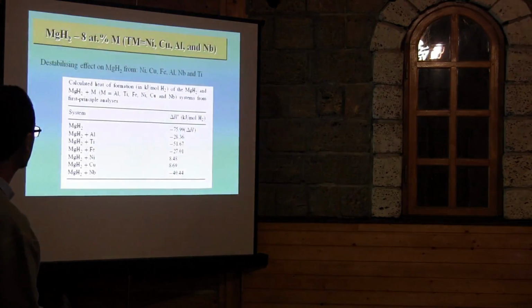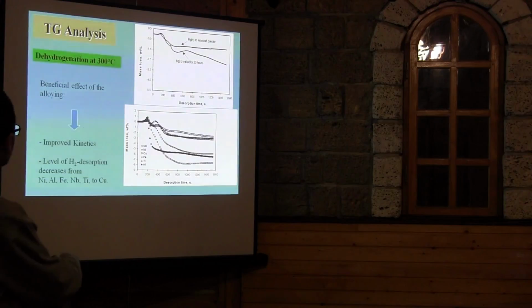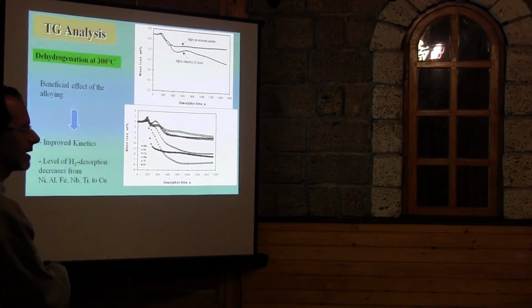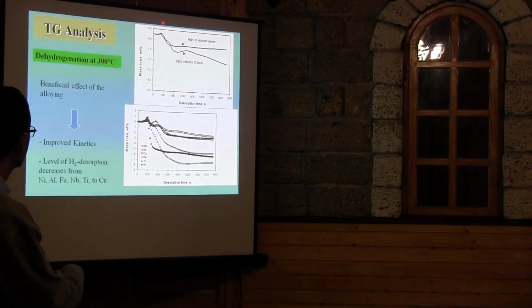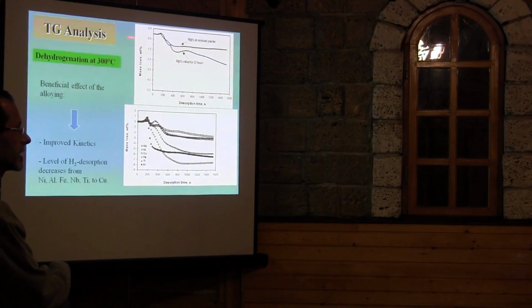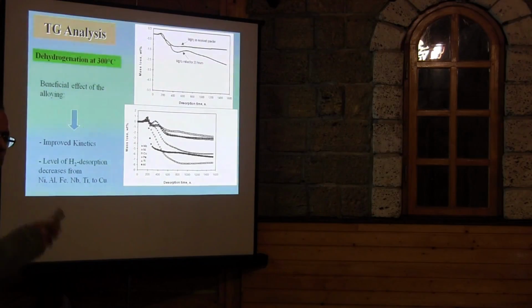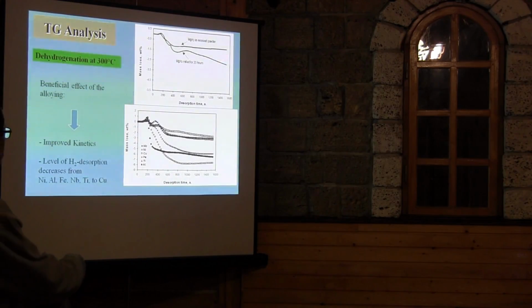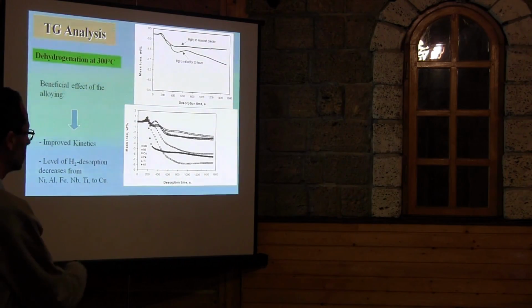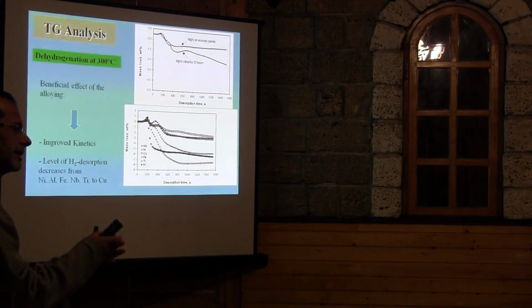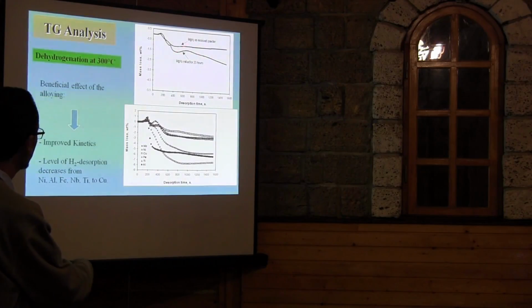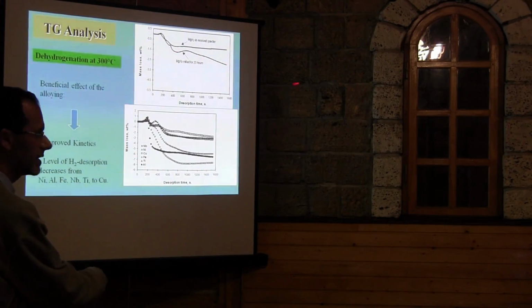Now, what is the thermodynamics of the system? I did what we call thermogravimetric analysis. I made the dehydrogenation at 300 Celsius. You can see, as received, when I buy magnesium hydride, it doesn't release hydrogen, even at 300. That's why I said it's very stable, and the kinetics is very slow. You cannot release. To get a better comparison, I also tested pure magnesium hydride in the same condition. Again, magnesium hydride releases very, very slowly.